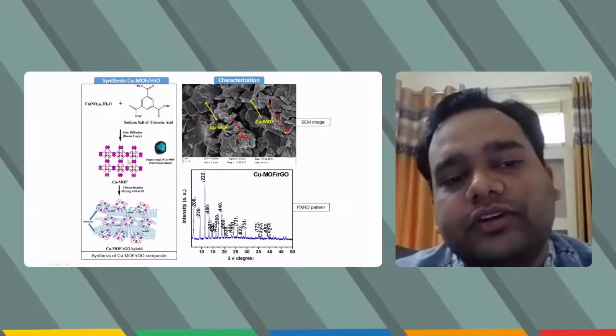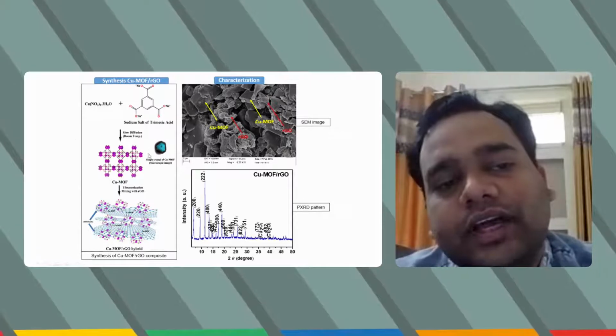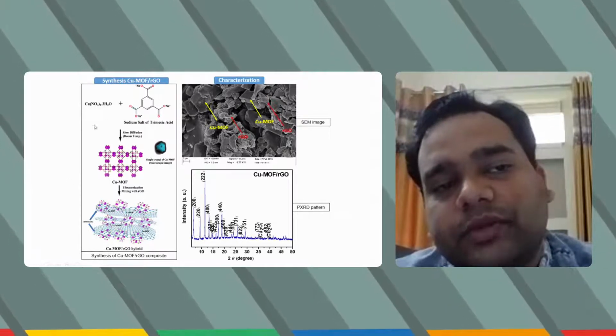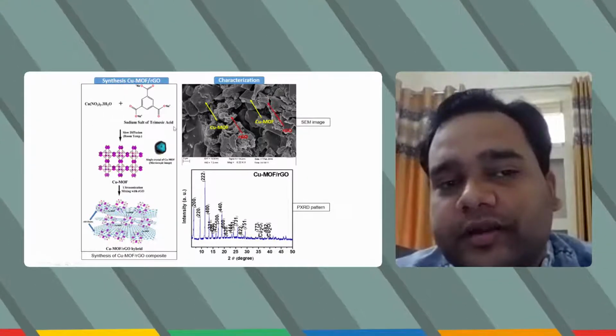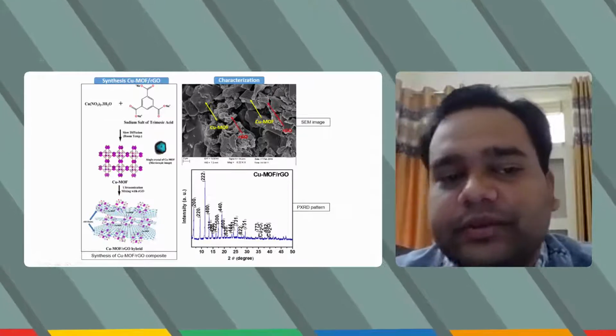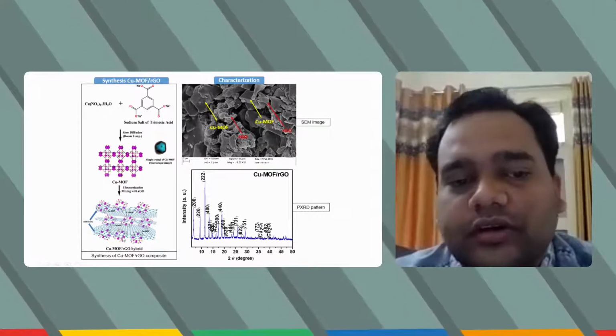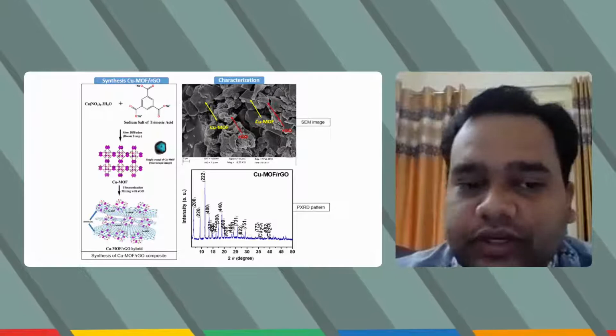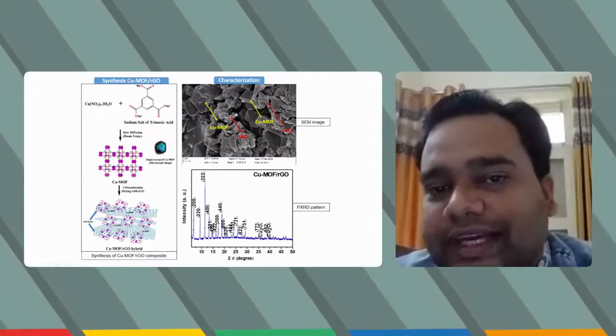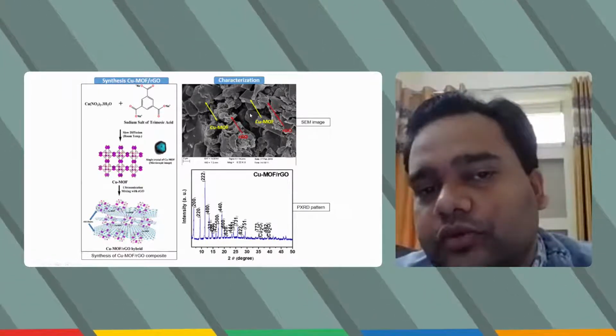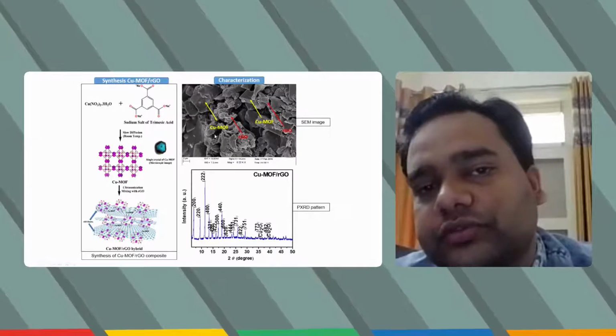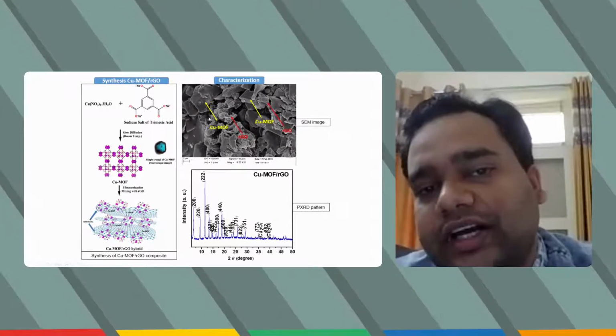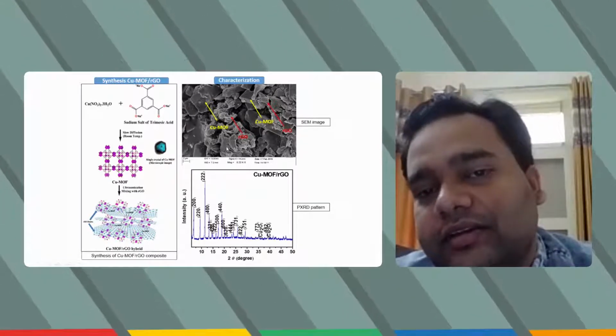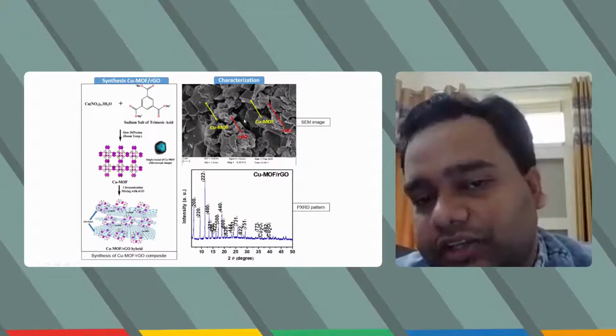So these MOF crystals were grown in a very simple slow diffusion reaction with copper nitrate and trimesic acid, and then we mixed it with reduced graphene oxide by the ultrasonication method. And you can see from the SEM, scanning electron microscopy image, that two types of structures were observed. In the background, you can see large crystals of copper MOF and these graphitic agglomerates of RGO.